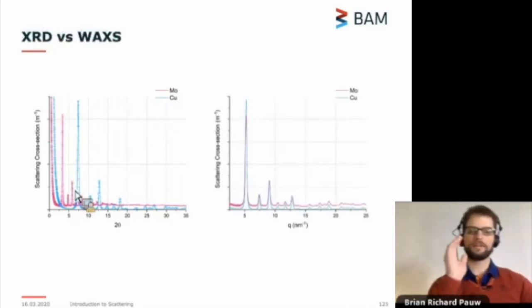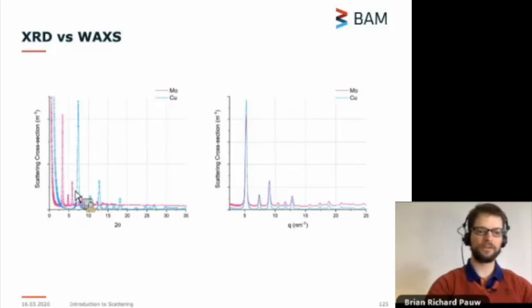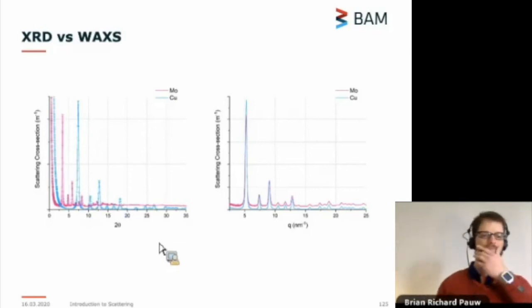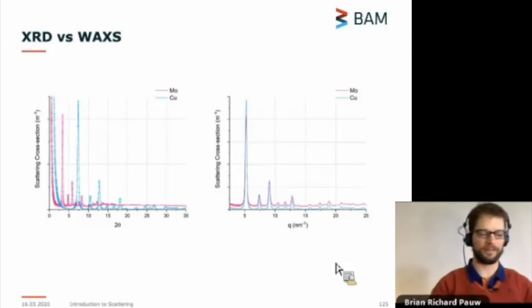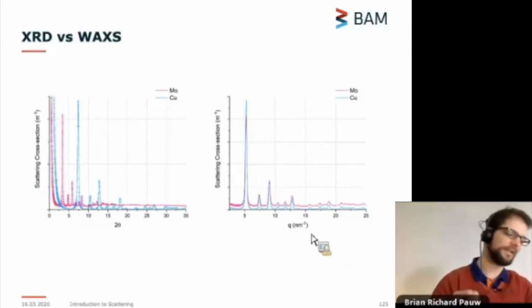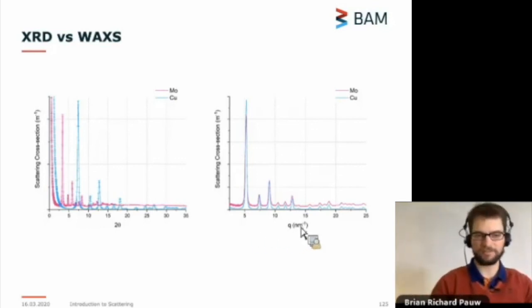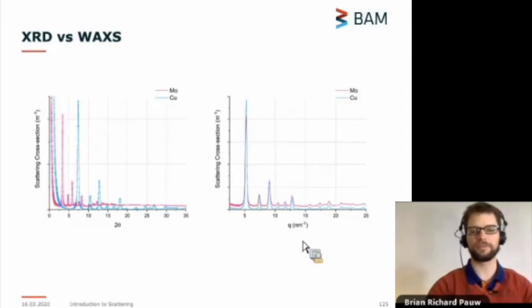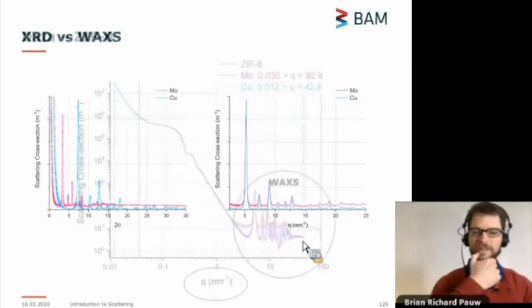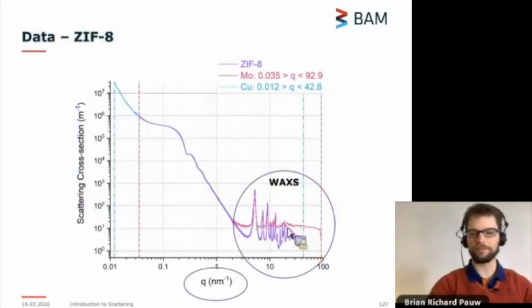Now, I've seen this a couple of times, and I really recommend not to do this. I see that some diffractionists take this molybdenum signal and recalculate the 2 theta angles as if it were copper, and then analyze it completely as if it were copper. And this isn't right for multiple reasons, but the main reason is that these signals actually are not the same. What you measure with molybdenum isn't necessarily the same as what you measure with copper. The crystalline lattice is the same, but you see there's a difference over here in the signal. The molybdenum signal is a lot higher than the copper signal.